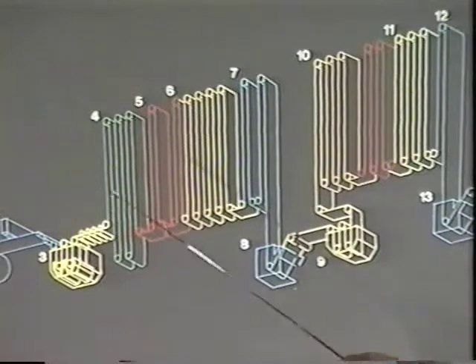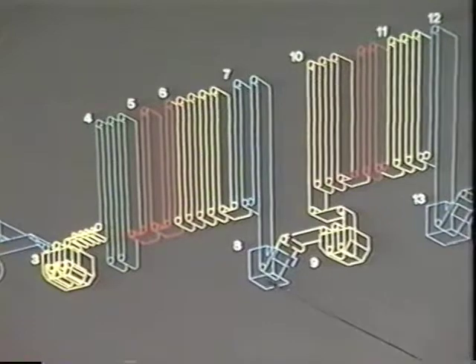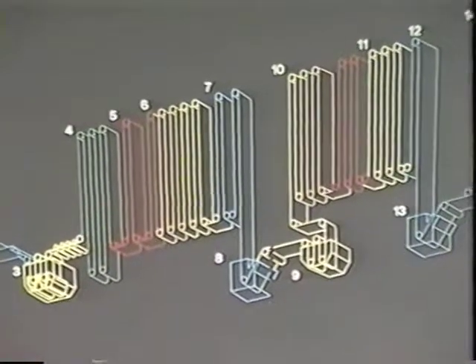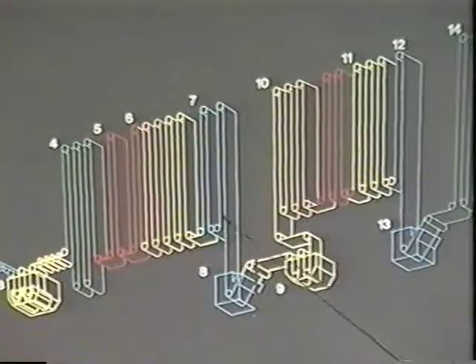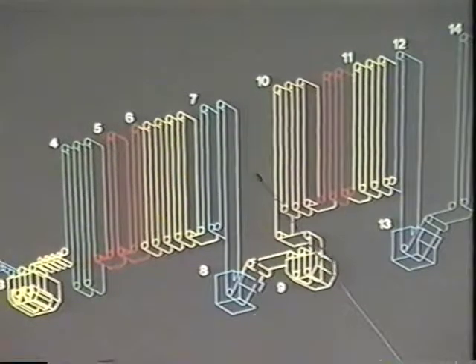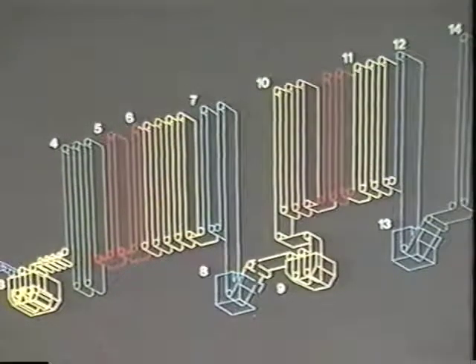So you heat a single strip up to 1,300 degrees or 1,500, depending upon what kind of product you're trying to build. Then you rapidly cool it down and quench it. If we're building high-strength steels, we'll take advantage of this process here and manipulate the cooling rate so that we can build extra strength. This is how we build dual-phase products.